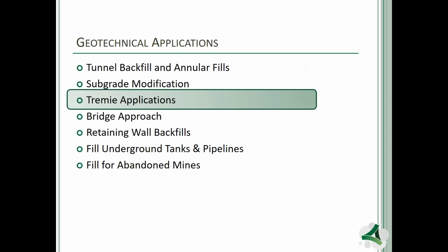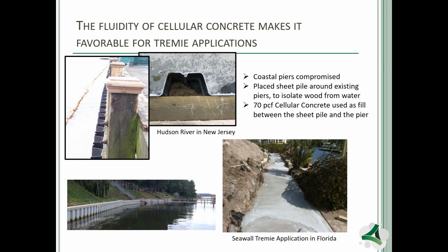Since we're talking about buoyancy, that brings us into the Tremie applications. Anytime we do Tremie applications, we have to displace water, and we will have to go with at least 65, 70 pound per cubic foot material to displace the water on a project. Having said that, if I can dewater a site, I would prefer to dewater it, place a lighter cellular concrete in its place, and make sure we have the appropriate amount of overburden to counteract any buoyancy concerns. The other option, I'll get back into that in a minute, would be to utilize a pervious cellular material to allow the infiltration of water to assist with counteracting the buoyancy factor of the material. But if you cannot dewater, you will have to Tremie the application with 65, 70 pounds per cubic foot material.